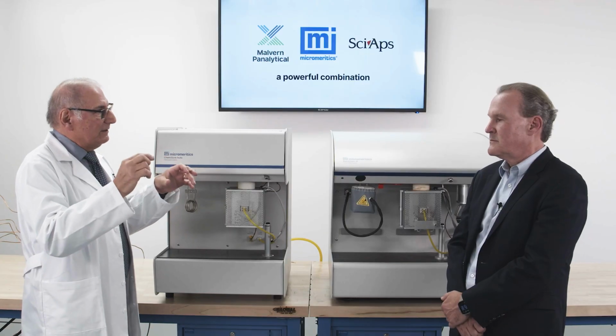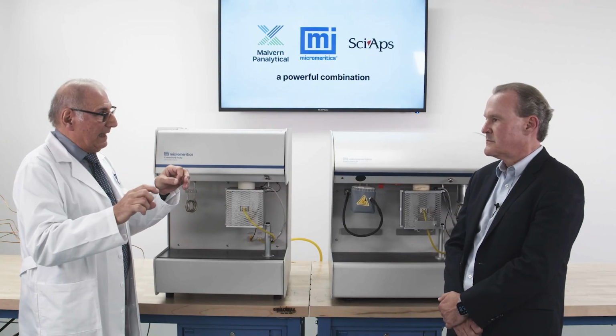The zeolite provides acid sites with H+ ions, which attack the methanol and dehydrate it into dimethyl ether. And as we keep going with the temperature, the second acid attack will go from dimethyl ether to olefin and other products. In this case, we have to characterize the acidity of the sample.